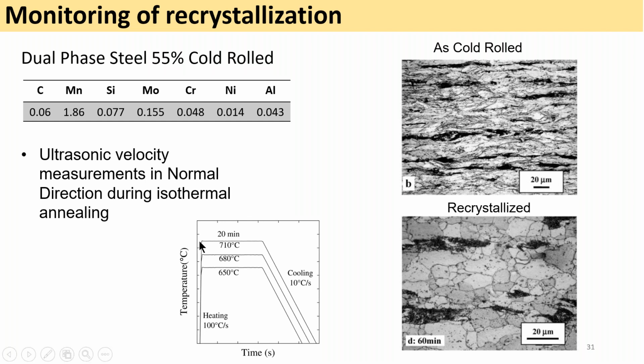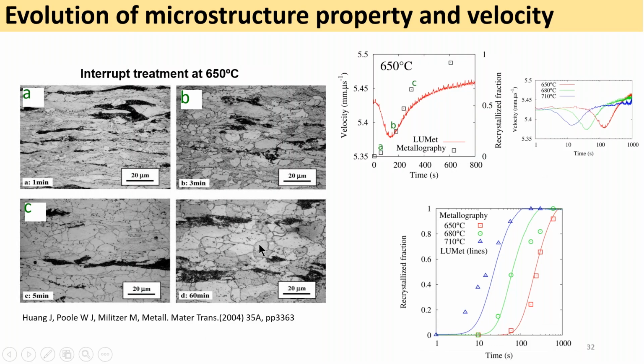What we are going to do is evaluate the change in velocity during this isothermal holding. So I show you here the velocity with respect to time during this isothermal holding. What you can see is that it does change in a non-expected fashion, I would say. I guess this is because we have a change in texture in the sample during recrystallization, and this change in texture involves a change in the distribution of orientation of grains. And you can see here the corresponding microstructures: stage A, where the recrystallization has barely started; B, where the recrystallization is partly going on; and C, where the recrystallization is almost completed.